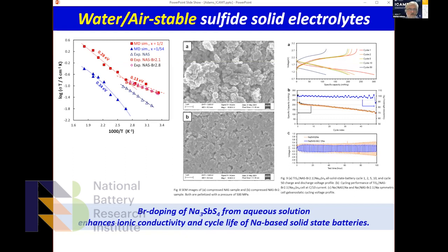And with that, we get material with higher conductivity by the bromine doping in this case, and you have material with better interfacial properties. Because the material fails at the anode, but it fails in a way to produce sodium bromide, and that forms a kind of stable, very thin layer, not too high resistance, and with that, the overpotential remains very stable. Without the doping, you see it slowly decomposes, and the overpotential becomes higher and higher.